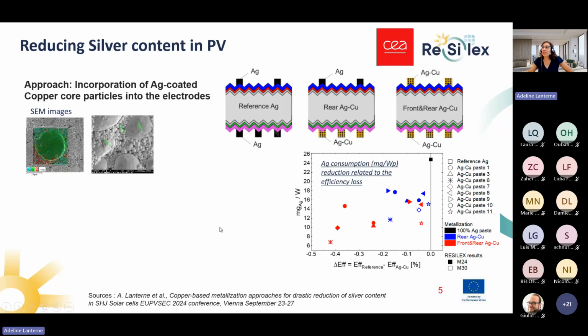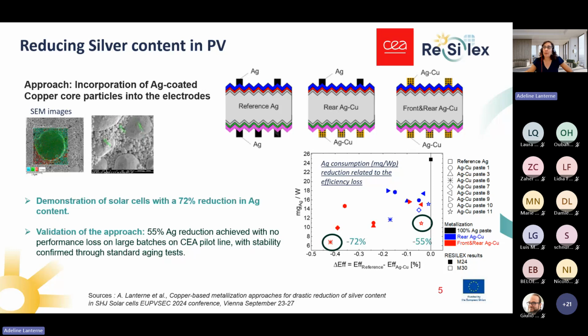On the graph here, you can see the silver content per watt, how we could reduce it, and the impact on the cell efficiency. In the end, we could demonstrate solar cells with 72% silver reduction, so we reach 7 milligrams of silver per watt. And we could validate the approach for a reduction of 55% of silver approximately, where we have no efficiency loss, and we also could confirm for this particular configuration that we have stable performance through standard aging test.